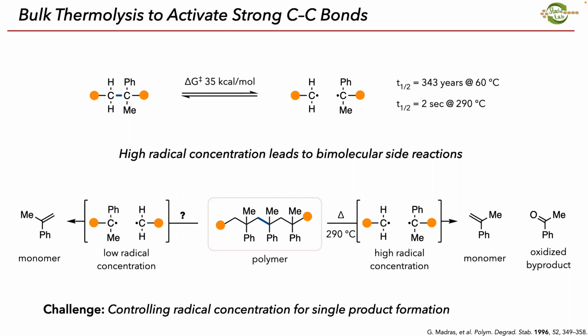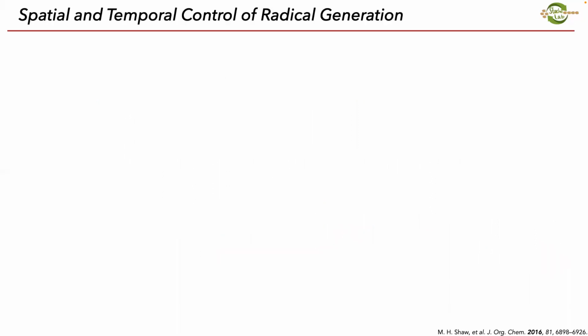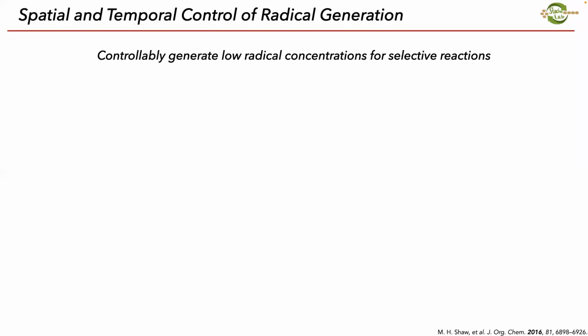Instead, if we can find a strategy to generate a low radical concentration, then we can pull off monomer and not have any of these side reactions and get a clean monomer stream. And so this is the question we asked. How can we controllably generate low concentrations of radical for selective reactions? And over the past 15 years in organic chemistry, we've done this using photocatalysis. So we use visible light to generate radicals with controlled concentration and temporal control. The light's on, you're generating radicals, turn the light off, it stops.